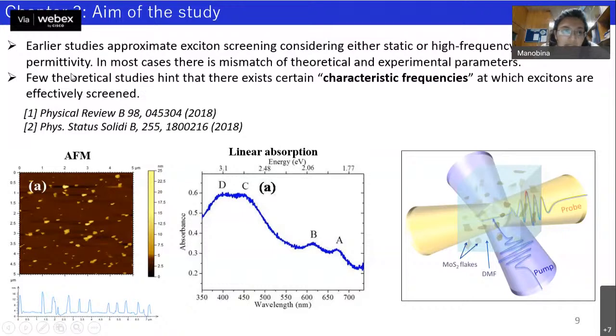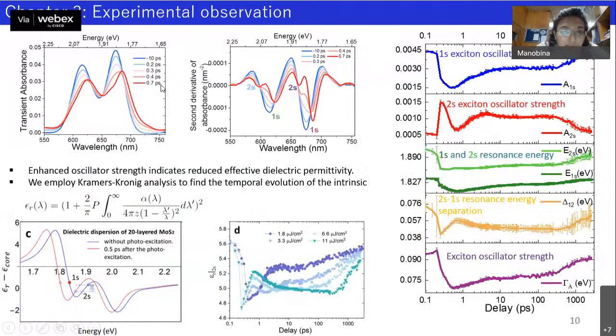This is a prediction, but usually some studies approximate screening through the dielectric permittivity either at optical frequencies or at the static frequencies, and none of which exactly matches with the experimental results. So here we try to find these characteristic frequencies. So we use a transition metal dichalcogenide, MoS2, which shows excitonic absorption peaks, and it is atomically thin, so thickness is around 12 nanometer. We use pump probe geometry. Basically we observe the time dependent absorption of these excitonic peaks.